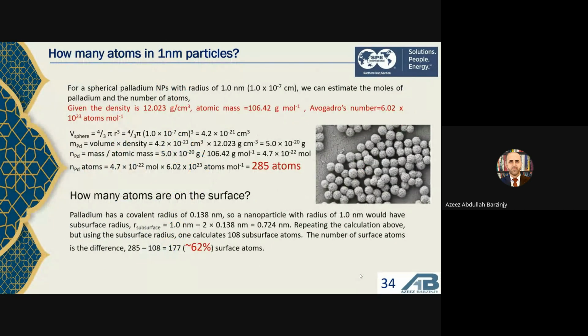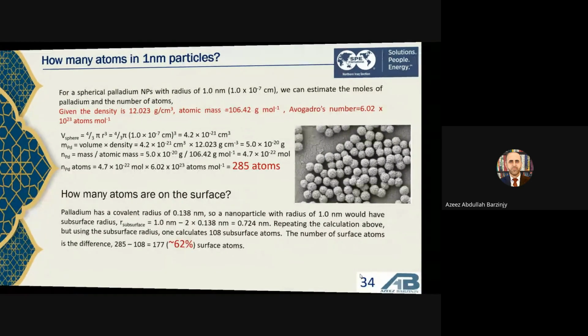So here I made a calculation for palladium nanoparticle this time. The radius of the palladium nanoparticle is 1 nanometer only. Then I calculated how many atoms of palladium I have in this 1 nanometer nanoparticle. So it was 285 atoms. And then I calculated also the surface atoms. So it was 177 atoms, which is precisely about 62% of the atoms. So 60% of the atoms will be on the surface, and only 38% will be inside. So this is the beauty of the nano size.